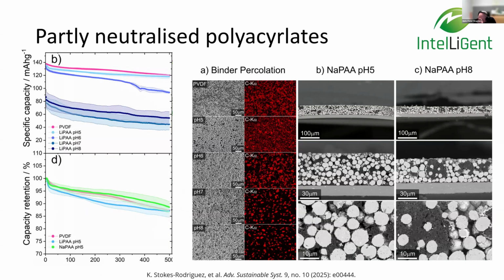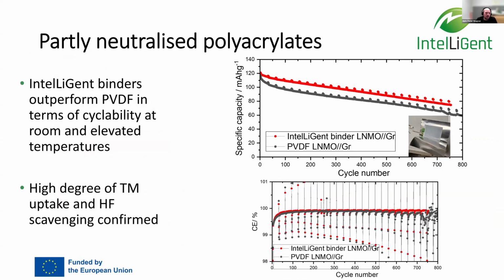At SINTEF, we've been working quite some years with polyacrylates as binders for cathodes. And here's an example of our research prior to Intelligent. We worked on lithium and sodium PAAs. And by partially neutralizing them, we can actually get really nice processable binders that have performances as good or better than PVDF. We continued this work in Intelligent, and we can happily say that our binders actually outperform PVDF references, and in our opinion, they work better than CMC binders.